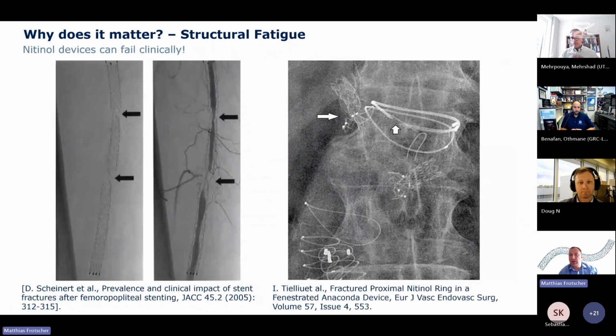The following slides show some clinical examples of nitinol device fractures, and in this example, a self-expanding nitinol stent is shown 9 months after implantation, and it has a severe stent fracture in the distal and a moderate stent fracture in the proximal part of the stent. And angiographically, both lesions were associated with a restenosis larger than 50% in diameter reduction. So this is dramatic for the patient, which means that the lumen is less than half of what is intended to be by actually stenting this position in the artery.